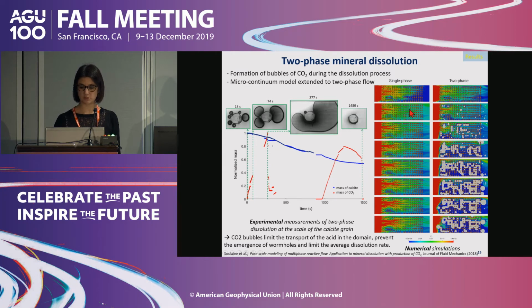So here this is a simulation for the single phase for the ramified wormhole regime. And here this is for the two phase, where now the timescale of dissolution of the CO2 in the aqueous phase is negligible compared to the timescale of production of CO2. In this case, you can see that small bubbles are created. Again, they grow, they coalesce, and at some point they form flow barriers for the flow. So these CO2 bubbles really limit the transport of acid in the domain, and they prevent the emergence of wormholes, and they limit the average dissolution rate.